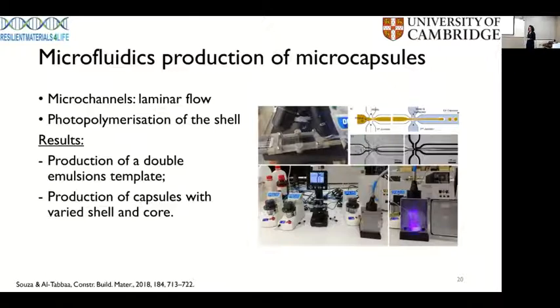And why is this important? Because then you can use that double emulsion as a template for producing microcapsules. You do that by exposing these double emulsions to UV light. What happens is that the middle layer polymerizes and you have a solid shell and a liquid core.